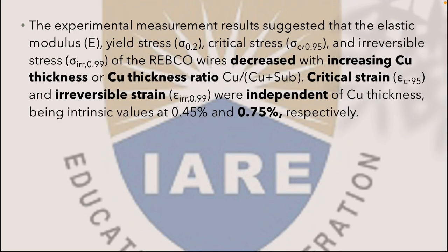The experimental measurement results suggest that the elastic modulus, yield stress, critical stress and irreversible stress of the REBCO wires decreased with increased copper thickness or copper thickness ratio. Critical strain and irreversible strain were independent of copper thickness, being intrinsic values of 0.45% and 0.75% respectively.